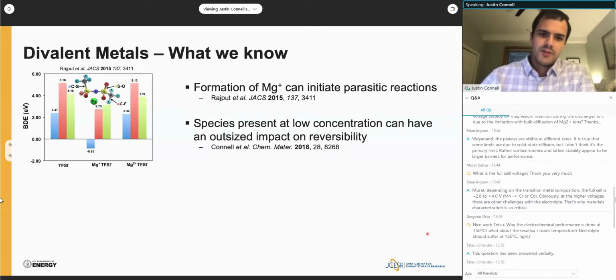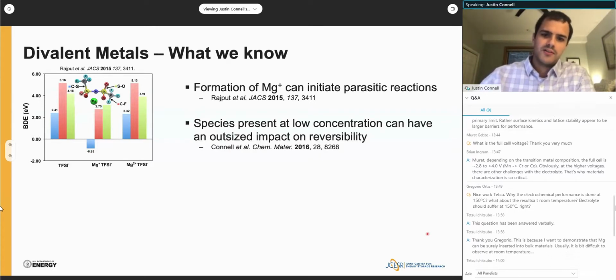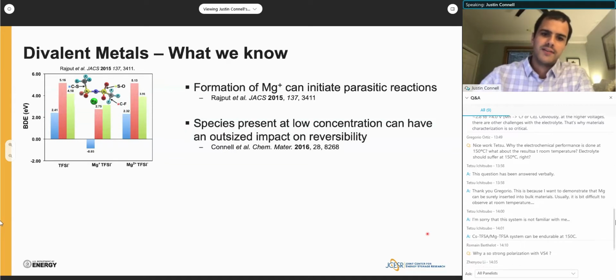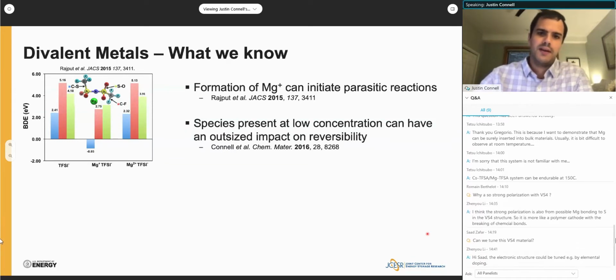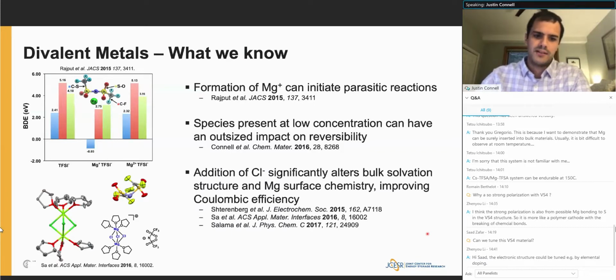In addition to this, it's been shown that species that are present at very low concentrations, even ppm levels, can have a really outsized impact on reversibility. So we need to pay attention to not only the majority species in the electrolyte, but also things that may be present even at minority concentrations. And finally, as the last speaker pointed out very nicely, the addition of chloride to a lot of electrolytes can really significantly alter solvation structure and magnesium surface chemistry, in a lot of cases leading to improvements in coulombic efficiency.